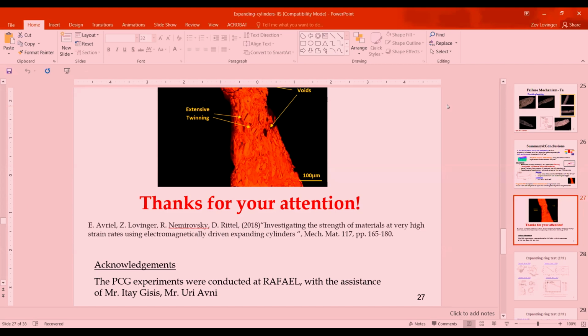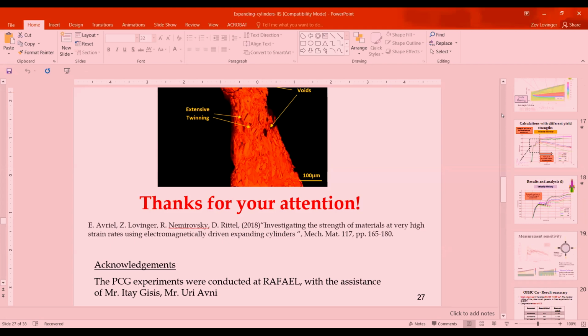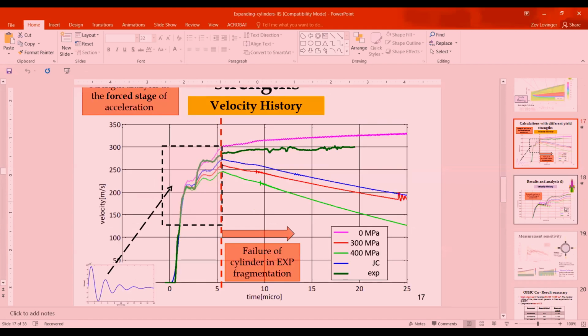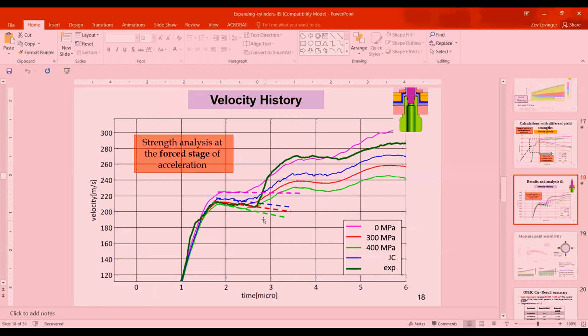Okay, sure. So the yield strength, as we're looking at the profile, we could see that these inclinations in the velocity profiles are correlated very strongly to strength. And we did a broad sensitivity examination of this, and you could get very good sensitivity. As I said, for copper, we got a sensitivity of just about 50 megapascals, analyzing this for different types of strength. Again, we're looking just at an elastically perfectly plastic (EPP) behavior. The information here can't give a hardening mechanism, etc., but it would give the overall strength we're seeing at this stage of acceleration of the cylinder.